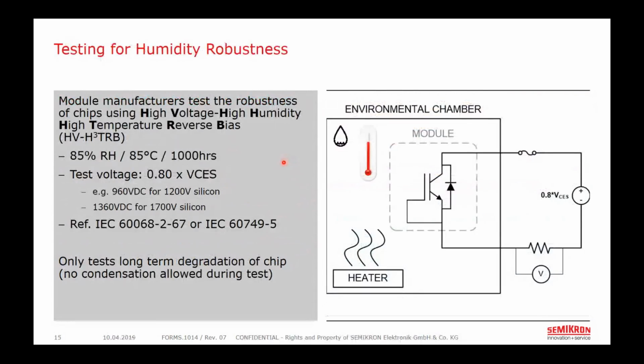The primary test for checking the robustness of the chip against these long-term corrosion effects is the high voltage, high humidity, high temperature reverse bias, or HV-H3TRB test. This is done by placing the power module inside a chamber with a fixed temperature and humidity and putting the semiconductor switch in the reverse blocking state. We place 80% of the device's rated blocking voltage across it, and we measure the reverse leakage current over a period of time. And with any luck, after a certain period of time, typically a target of 1,000 hours, the device still blocks its rated voltage and doesn't show any signs of the corrosion we just described on the last slide.